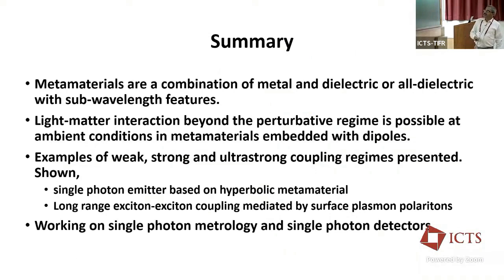Right. Just to summarize, metamaterials are a combination of metal and dielectric or all dielectric scattering elements with sub-wavelength features. So what I showed is that light matter interaction beyond the perturbative regime is possible at ambient conditions in metamaterials with embedded dipoles. Right? So I showed examples of weak, strong, and ultra strong coupling regimes, and showed the single photon emitter based on hyperbolic metamaterial and long range exciton-exciton coupling mediated by surface plasmon polaritons. We're currently working on single photon metrology. This is the lab which we are setting up.